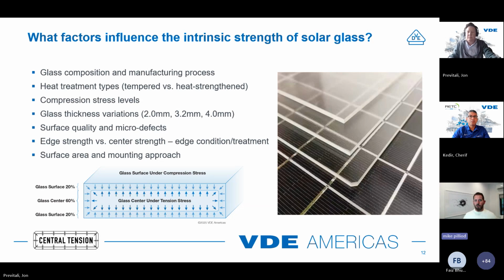Within the solar world, and this isn't 100% true, but the predominant glass in crystalline solar is patterned rolled glass, where they roll the soda lime glass through rollers to create either small bumps or some kind of texture onto the glass, and then go through a lamination process and cutting and grinding. Float glass is also used in solar as well, so it's not 100% rolled, but it is the primary one.